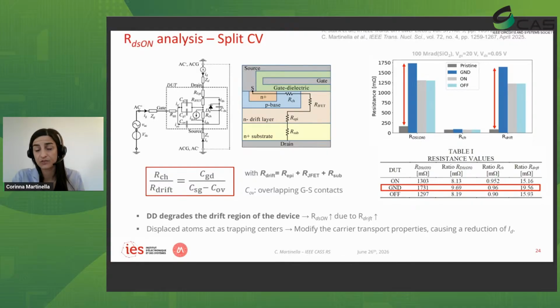Here we have the total on-state resistance of our component, which is the sum of all the resistances of the device. We can see this was the pristine level, I think it was 80 milliohm. And after irradiation, if we consider, for example, the device irradiated at ground level, we had about a factor of 10 increase. No, sorry. The value was almost 2000 milliohm.